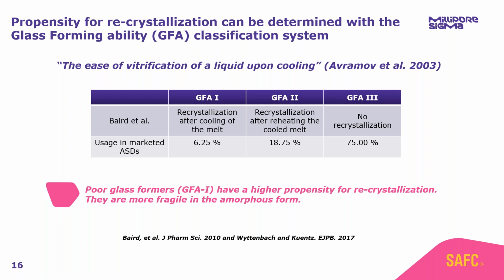In short, they proposed DSC as a method to determine this, and they placed the molecules in a DSC pan. They melted the molecule to remove the crystallinity. They then cooled it right back down to solid and then melted it again. And they observed the differential scanning calorimetry curves in this melt-cool-melt cycle. And depending on if and when they observed crystalline behavior, they categorized molecules into 3 different buckets. So firstly, we have the GFA class 3. These are also known as good glass formers. These are molecules in which no recrystallization was observed in that entire melt-cool-melt cycle.